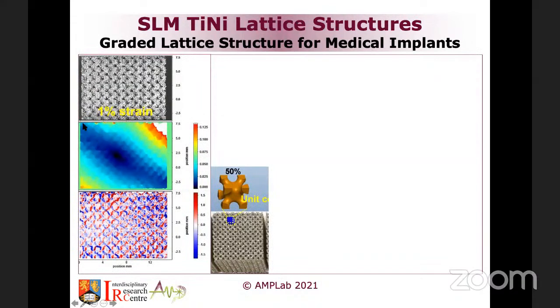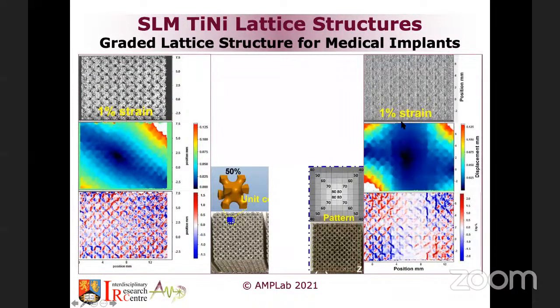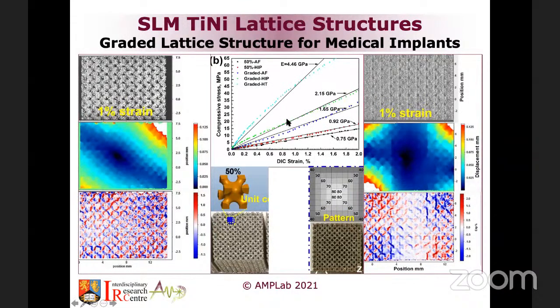And what we found is that in a uniform lattice, this is a strain map to show how deformation happens, we had that kind of 45-degree profile of a strain map when a load is applied. But when we applied that on a graded lattice, we saw some sort of central shrinkage in the strain, potentially looking like how you would squeeze a sponge, how you apply a load to a sponge. And that basically resulted in a much lower elastic modulus, reaching sometimes around 4.6 down to 0.75 gigapascal. So that managed to generate a very low modulus material that is actually very close to human bones, and it's also a biocompatible material from that point.